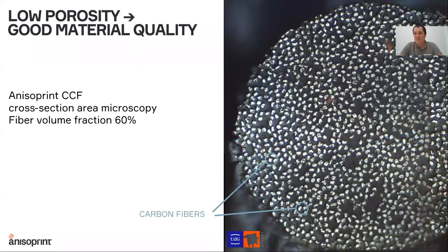Gray inside, between the fibers, you can see gray matter. It's resin, which bonds together these fibers. So you can see that there are no black spots, no irregularity in the fiber distribution. So it's considered to be a very good quality impregnation with a fiber volume fraction of about 60%.